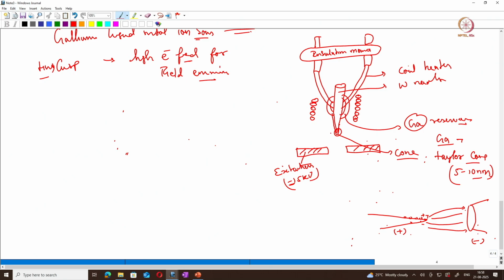Okay, so here this tiny cusp has a very high electric field, for the field emission, which is around 10 raised to the power 10 volt per meter. This electric field concentration is enough to field evaporate the liquid gallium into gallium ions, correct? So now we will talk about the gallium ions. This is the gallium reservoir. The gallium ions are extracted from the Taylor cone.